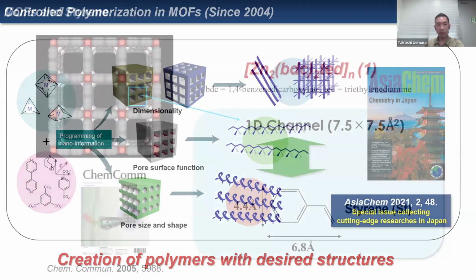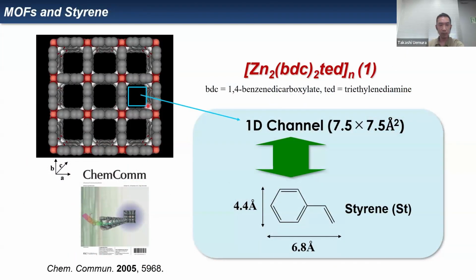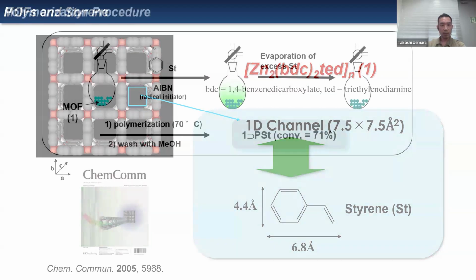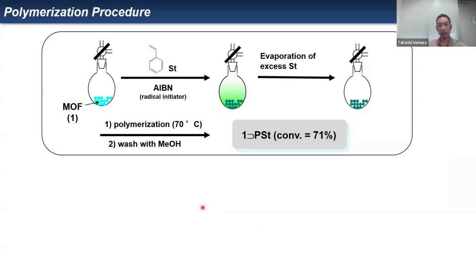Okay, the first work is with this type of MOF composed of zinc ion and BDC ligand. Because the size of this MOF's 1D channels is suitable for incorporation of only a single conventional monomer such as styrene. So here let me show you the polymerization procedures. How can we perform the polymerization? First, the MOF powder was immersed in styrene liquid with AIBN as radical initiator to incorporate the monomer and initiator into the channels.